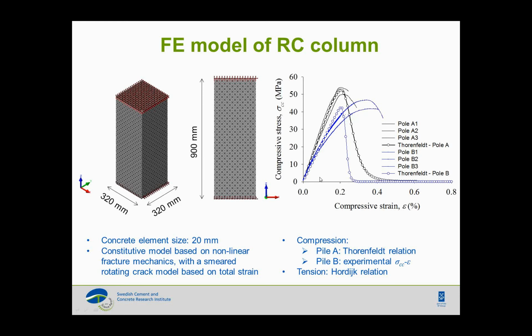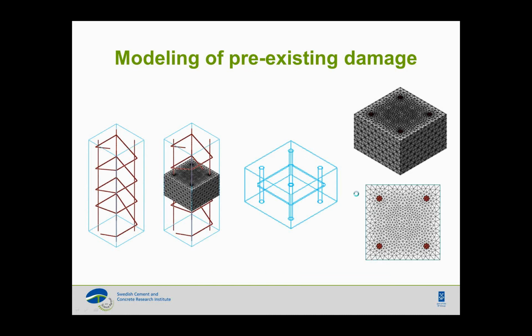We also thought that it's important to try to induce the pre-existing cracks in our model. So we looked at only a thin section of the piles in our model and tried to use our corrosion model, but this time to have the swelling effect due to sulphate attack. The expansion was taking place in the cement paste. It was not around the reinforcement.